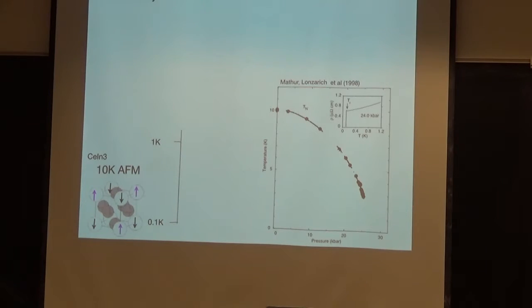but with the notion that quantum criticality can lead to superconductivity, this idea was then followed by Lonzarich and co-workers at Cambridge, and they put pressure on cerium indium 3, and when they did so, they discovered that indeed, as they expected, T_N went down, and lo and behold, a tiny 0.2 Kelvin superconductor was formed around the quantum critical point. This is 10 T_c. If you were to actually draw this, it would just be a tiny minute bump on this scale.